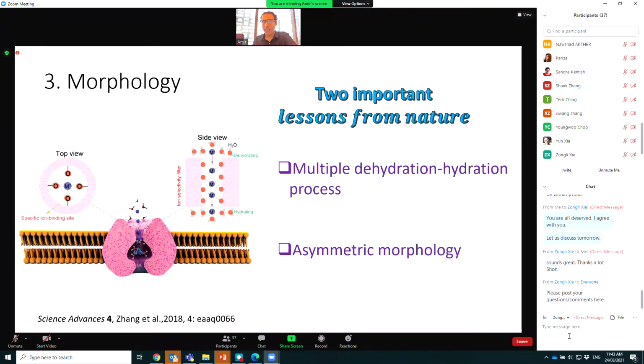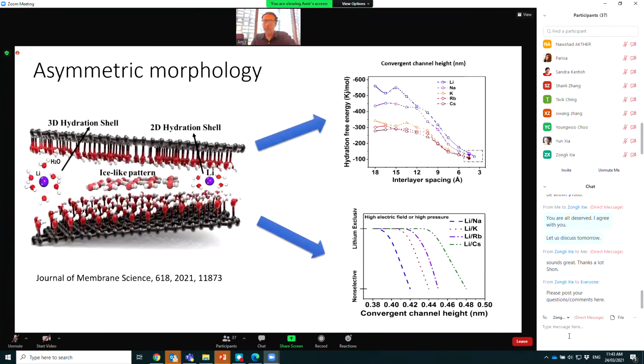One thing that is clear in almost all of these biological ion channels is that they have asymmetrical morphology, or at least they have a sort of asymmetrical element. This asymmetrical element could be in morphology or chemistry or wettability. Using that sort of asymmetric element within their structure, they manage to overcome the trade-off between low selectivity and permeability. We just published very interesting results in the Journal of Membrane Science based on this concept. We tried to study how this change in morphology contributes to selectivity, and what the mechanism behind that is when it comes to the separation of lithium ions from other monovalent ions.